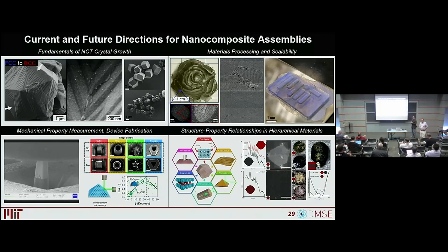Yeah, thank you for a great talk. For this type of NCTs that you are crystallizing, what is the approximate volume fraction of the inorganic part, and what is the approximate fraction of the organic part? Variable, but I'm going to have to do the math in my head. The lowest I'd say is probably 5 to 10%, and the highest is pushing 50-ish% volume fraction. And especially for low inorganic fraction materials, can I think about it as a polymer with pinning points and inclusions, and what can it give in terms of materials properties?